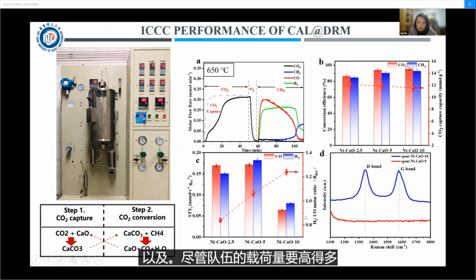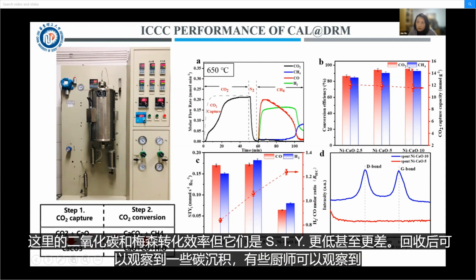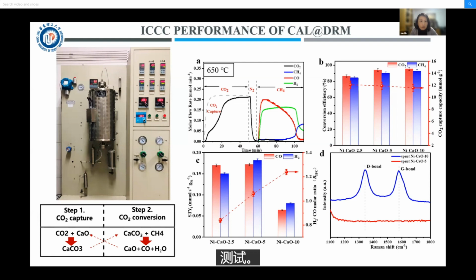Although the higher nickel loading has a very high CO2 and methane conversion efficiency here, their STY is lower and, even worse, some carbon deposit, some coke, can be observed after the recycle test.